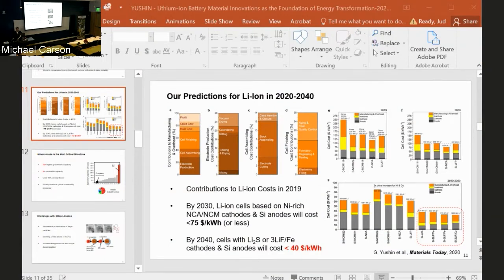In the meantime, when I joined Georgia Tech over a decade ago, we saw that multiple of these challenges could be overcome with smart materials engineering. So for example, if you move to smaller particles, you can stabilize mechanical issues with this chemistry. Unfortunately, small particles also have very high surface area and still suffer from electrochemical instabilities. We also learned that if you form composite materials, you can dramatically reduce swelling or volume changes at the particle level. And finally, if you figure out how to produce particles with stable dimensions and sufficient porosity to accommodate volume changes in silicon, then you can also stabilize the SEI, prevent electrolyte decomposition.